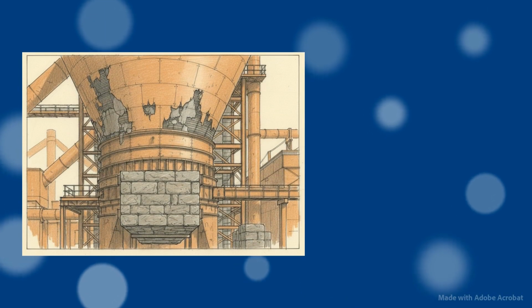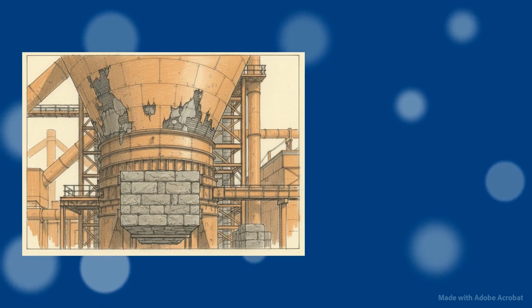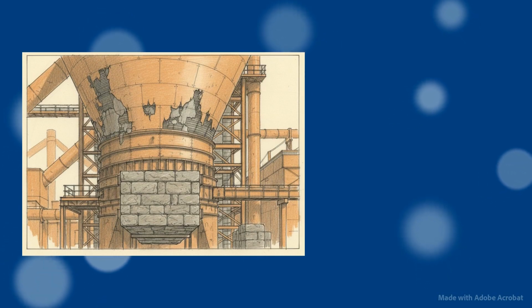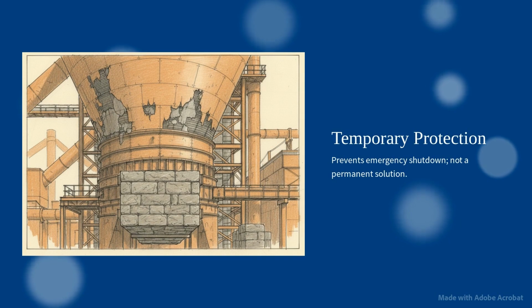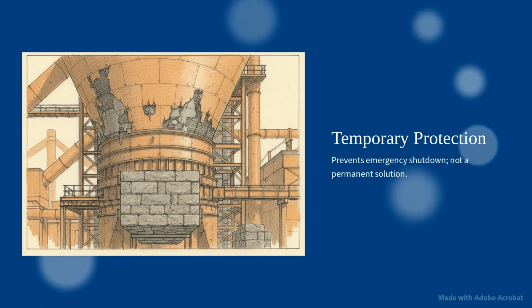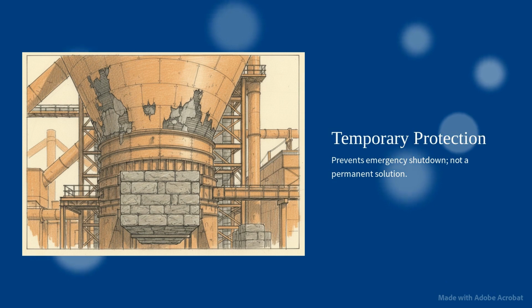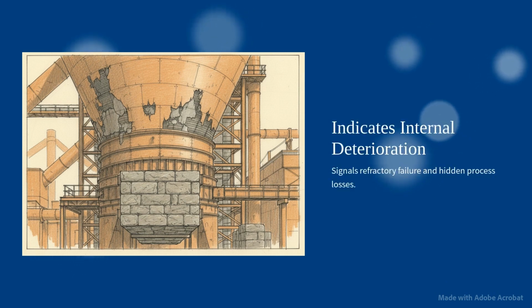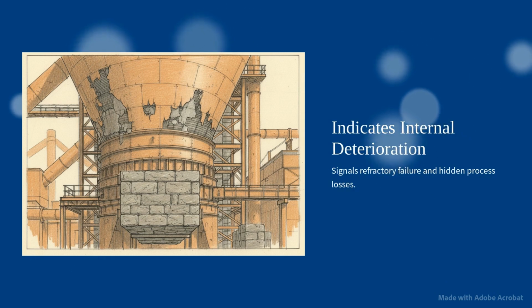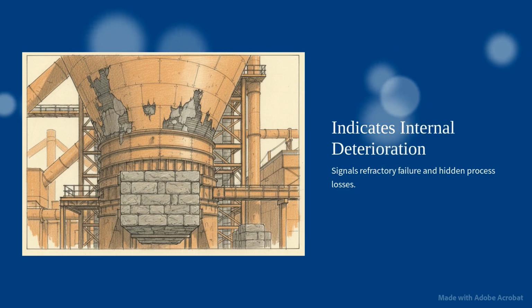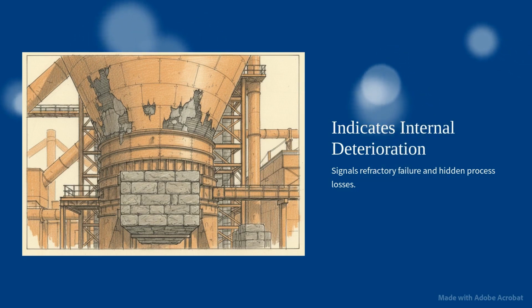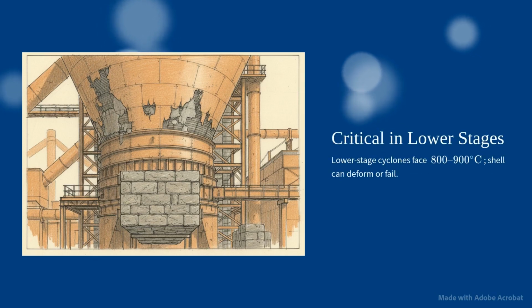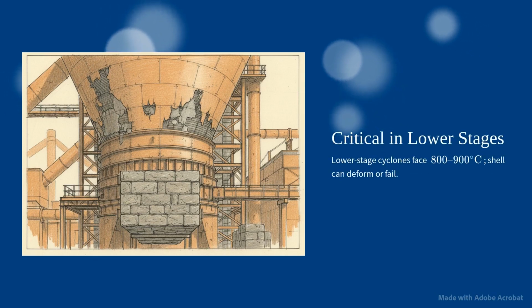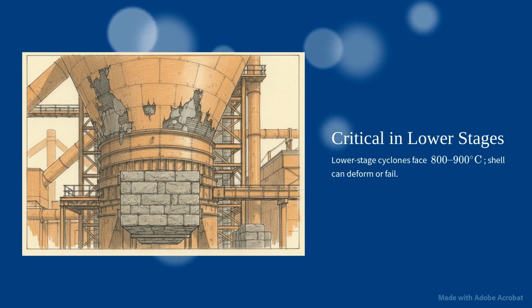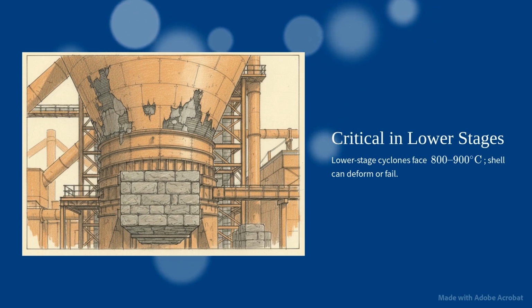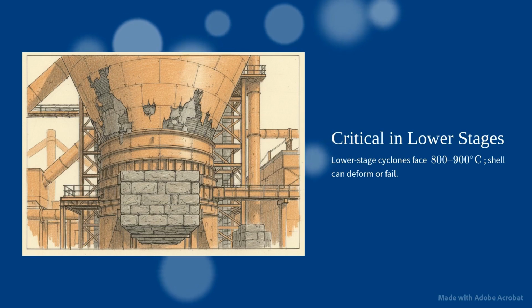Here's how stone boxes function and why their presence is a red flag for deeper issues inside the cyclone. Temporary protection is the main role of a stone box. It helps avoid an emergency shutdown, but it's not meant to be a lasting fix. A stone box indicates internal deterioration. Its presence means the refractory lining has failed, and hidden process losses are already underway. Stone boxes are especially critical in lower stage cyclones, where temperatures reach between 800 and 900 degrees Celsius. Here, the steel shell can deform or even fail if left unprotected.